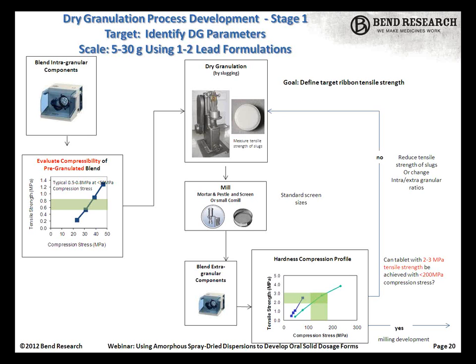And if you just look down the bottom left there, we will look at the compression profile. Here we'll be on the lower end of our pre-granulation blend. We'll generally target a tensile strength of our slugs of 0.5 solid fraction for the slugs, and then we will mill these into this 100 to 300 micron range, and then again do the hardness compression profile, which will be shown on the bottom right-hand side there.